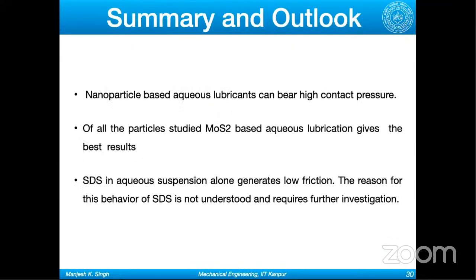To summarize, as I said, the nanoparticle-based aqueous lubricants can bear high contact pressure for all the particles studied. MoS2-based aqueous lubrication gives the best results, and SDS in aqueous suspension alone also generates low friction. The reason for this behavior of SDS is not understood and requires further investigation. This work I did in 2010-11 during my master's, and after that I could never go back, because in my PhD and postdoc I was working on other things. If you are interested, you are most welcome to look into these things in detail.